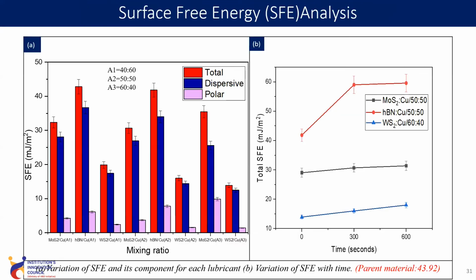Taking the total surface energy, it is observed that the minimum energy is obtained for the WS2 copper coating. As you can see, for the coating at the 60:40 ratio, because this coating, A3, is the mixing ratio 60:40 for the WS2 copper coating, it shows the minimum amount of surface free energy. It means it can show good self-cleaning and tribological properties, because it has the lowest surface free energy among all the coatings.